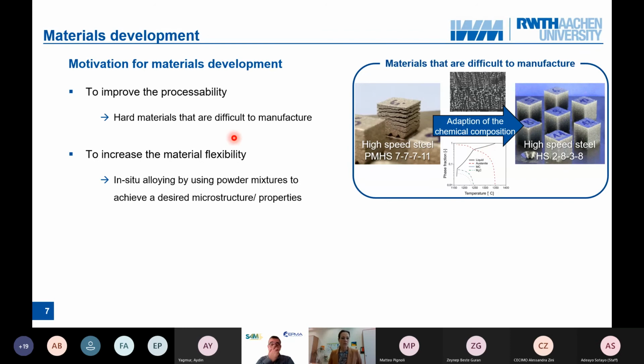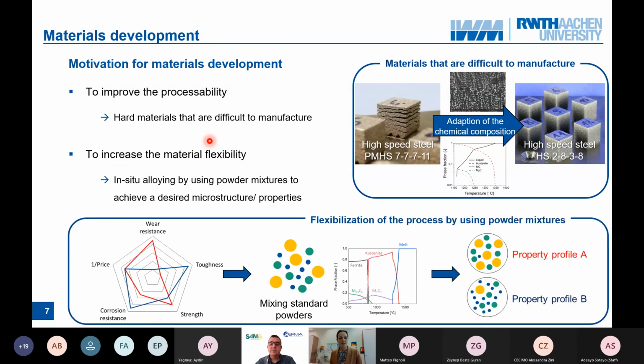And a second motivation for material development is to increase the flexibility. What does that mean? Additive manufacturing is known to be very flexible concerning geometries, but it is very limited concerning materials, because we only have some standard powders, and the range of these powders is limited. To increase the flexibility in materials, we have an approach to work with powder mixtures. That means we mix standard powders to get new alloys.